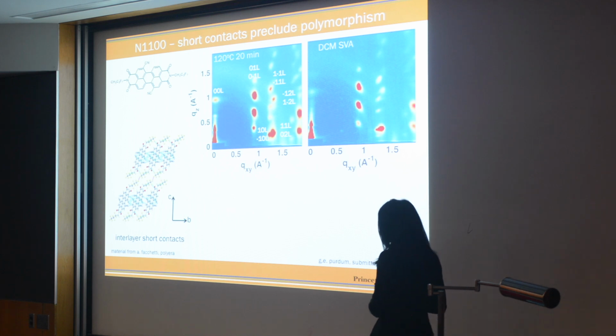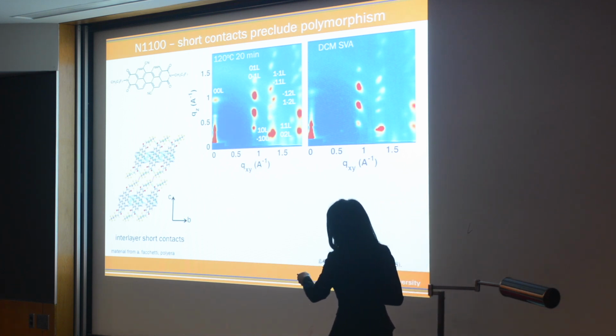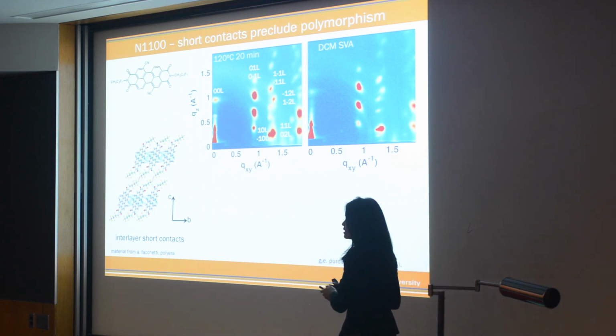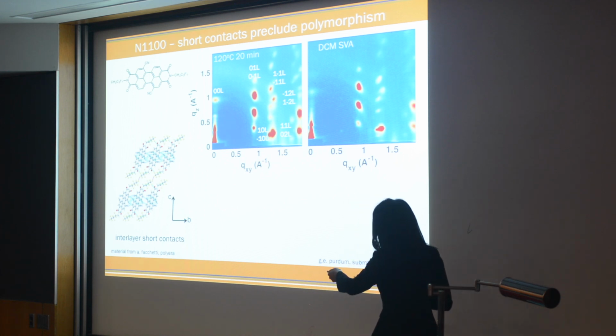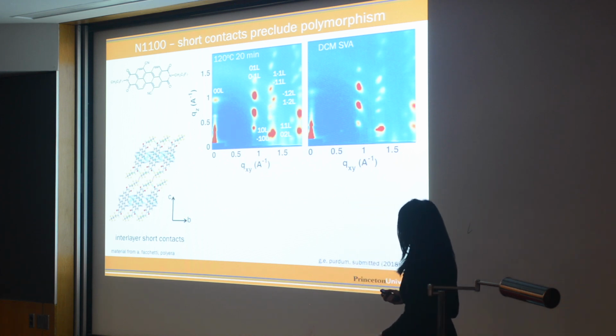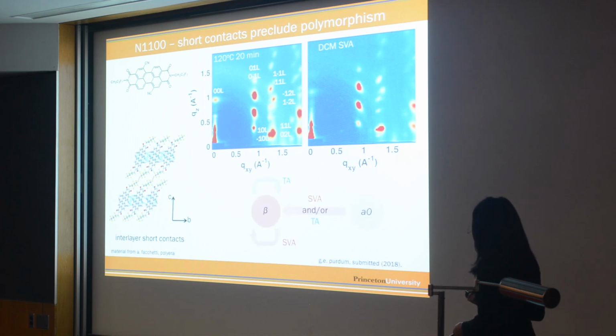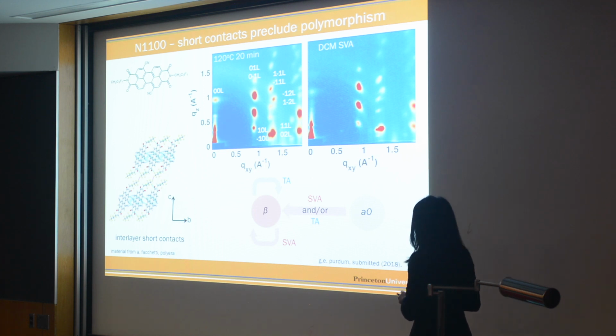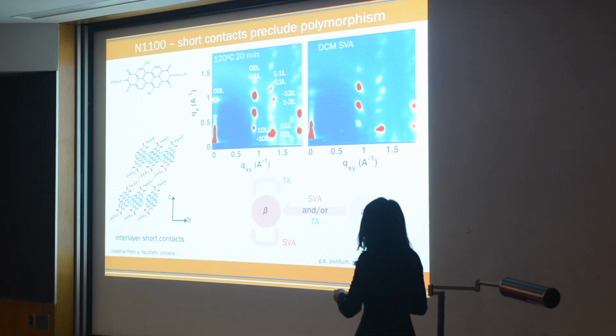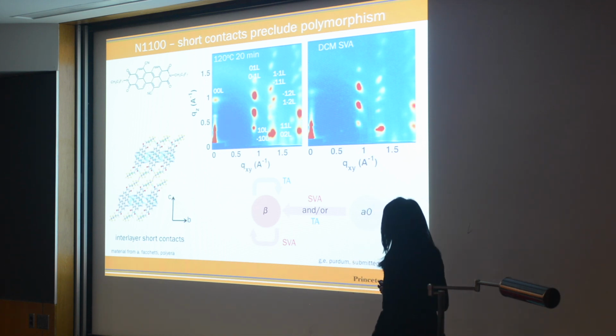This is N1100. That's the crystal structure. And again, here you see short contacts in the pi stacking direction, but you also see short contacts between the layers. These are X-ray diffraction data that tells us that we access an amorphous phase. And then it doesn't matter what we do, whether we solvent vapor anneal or whether we thermally anneal, we get back to the beta phase, and then we're stuck at the beta phase. Okay? It's got other polymorphs, but we don't access it. We're stuck at the beta phase.